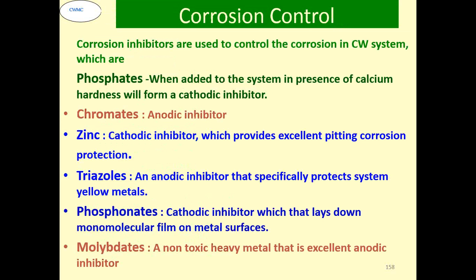Some of the important things are phosphates, chromates, zinc, triazole, phosphonates, molybdates. After that, chromates are generally ruled out these days because of the environmental considerations, and they are supposed to be toxic in nature, especially chromium 6+. Zinc is again a very good cathodic inhibitor, but there also being a heavy metal, the restrictions are it should not be more than 1 ppm in your water.